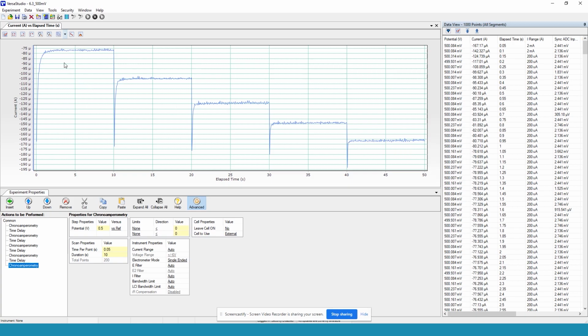Now, for the actual analysis, we have to take the steady state current, so one of these values, per each rotation rate, and plot 1 over the steady state current over 1 over the square root of the rotation rate. By plotting it this way for each different voltage, we make a nice Koutecky-Levich analysis of each voltage. And in this plot, basically, the slope represents part of the diffusion limited area, while the intercept is related to the kinetics. So by making the plot in this way for the different voltages, we can look at the contribution of each of these effects on the actual current that we are measuring.